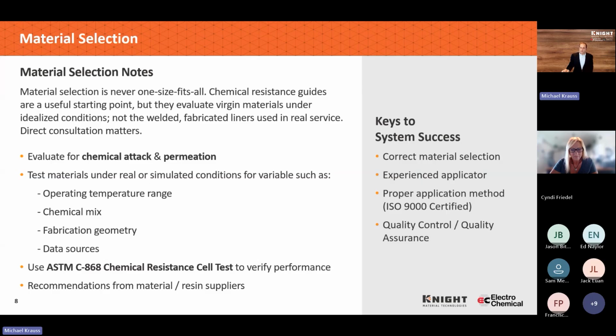There are some differences possibly in how it may change in color over time in certain surfaces. The suspension one traditionally turned a little bit darker brown in hot acid service. However, the emulsion, now that they had to move away from a PFSA-based emulsion ingredient, is browner to begin with. So I would say the type of polymerization would be the least of my concerns. Be more concerned about the specific grade, whether you need a homopolymer or a copolymer.